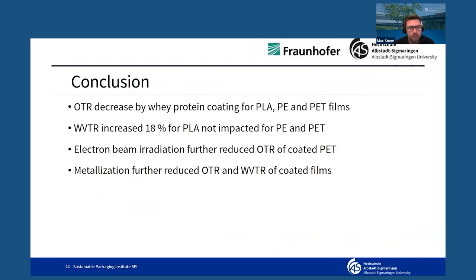So to conclude, for the oxygen transmission rate, we found a high decrease due to the whey protein coating for PLA, PE, and PET substrates. In some cases, the water vapor transmission rate was increased, but for PE and PET, this property was not impacted by the coating.